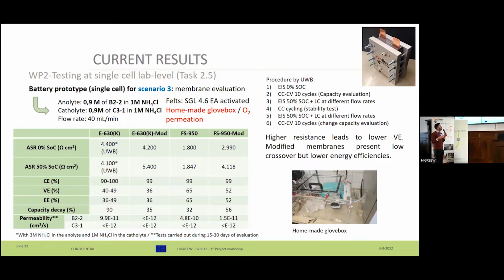So as we can see, when performing our modification, our membranes increase in resistivity, and this leads to lower voltage efficiencies then. And when compared between the different cationic ones, we found that the E630K was the most resistive, the one with more resistance. So they were discarded, even the commercial one. But I have to say that despite having more resistivity, the permeation of the active species was reduced.